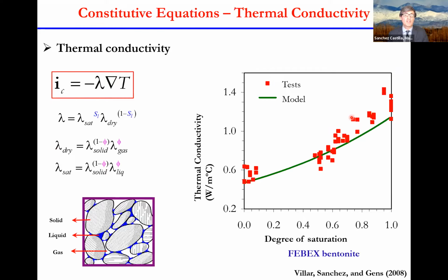Then in terms of the thermal conductivity, well, again, we have this typical Fourier law, but the challenge here is that the thermal conductivity does not depend on only one material, but on the different phases that we have in our porous medium: the solid, the liquid, and the gas. So we need to look for an equation for the thermal conductivity that allows us to account for the contribution of these different phases in the global thermal conductivity of our porous medium, right?